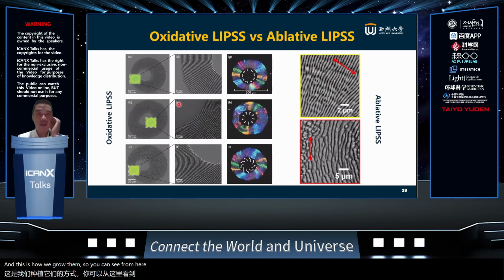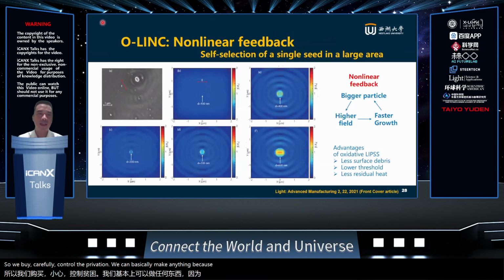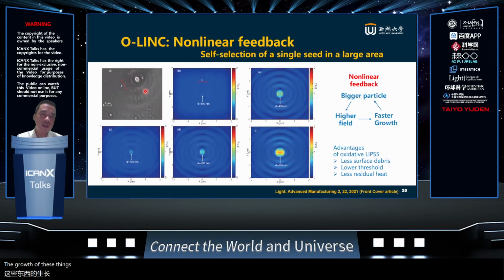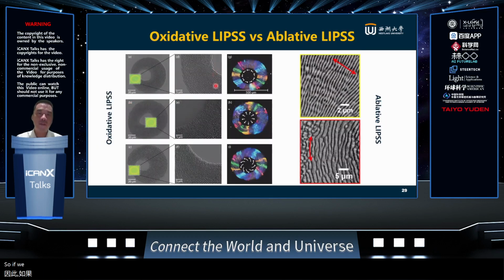So you can see from here, by carefully controlling the polarization, we can basically make anything, because as I said earlier, the growth of these lines, the oxidized lines, is based on the polarization of the incident laser. If we have circularly polarized light, they will grow like this. And if we have very complicated different kinds of polarization, by polarization control we can make lots of beautiful gratings. You can also see from the optical image that they give you shining rainbow colors. That's something I will show you later, and this basically inspired us to make structural colors out of it.